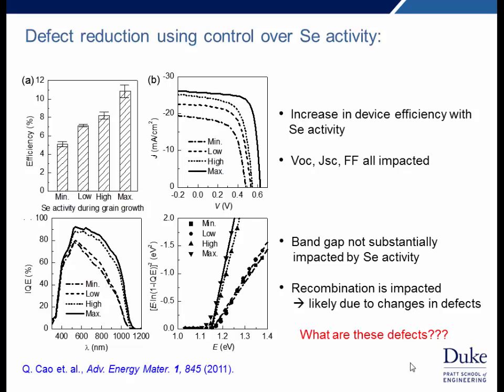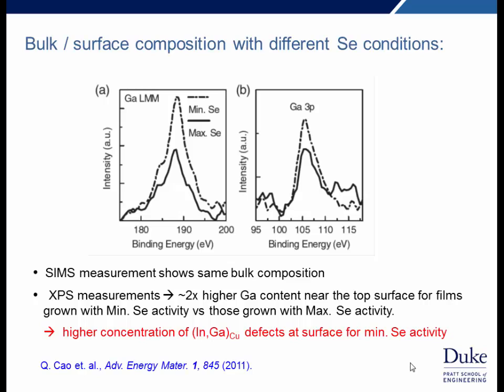And so the question is, where is this recombination coming from? What are the defects that are leading to this issue? If we look at SIMS depth profiling, we find that we get the same bulk composition. So this is consistent with the same band gap. However, looking at XPS, or medium energy ion scattering, there's clearly a higher concentration, 2 times higher concentration of gallium